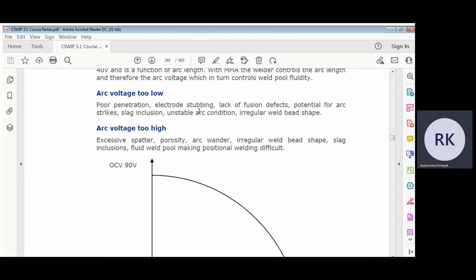So arc voltage too low, we saw current high and low. Let's see voltage too high and low. If voltage is low, poor penetration, electrode stubbing, lack of fusion defects, potential arc strikes, slag inclusion, almost the same thing as we saw in high current. So unstable arc, irregular weld bead, everything will happen.